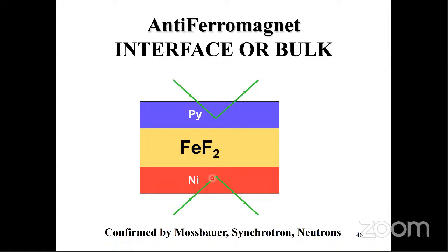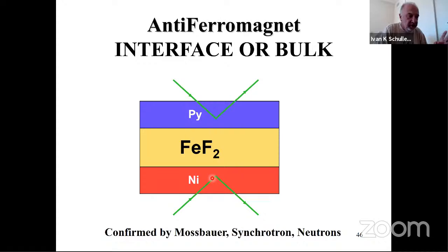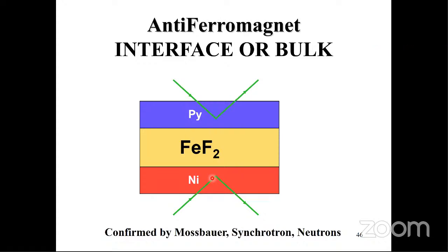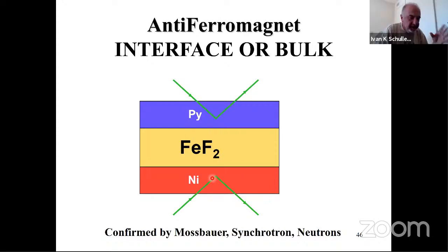Now what I will tell you is confirmed by Mössbauer and synchrotron studies. Let me show you a very simple experiment. I will take a nickel layer, which is a ferromagnet. I put iron fluoride on it, and we did this with manganese fluoride and cobalt fluoride also, and I put permalloy on top of it. So I have two magnetic materials, and there is an exchange bias at this interface, and at that interface. That's what I'm going to show you.